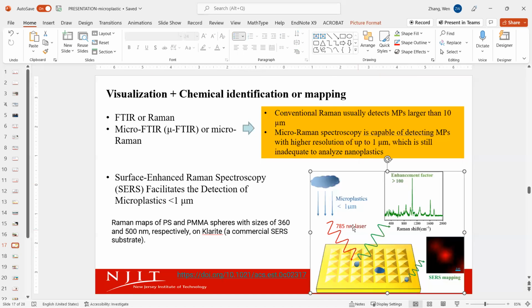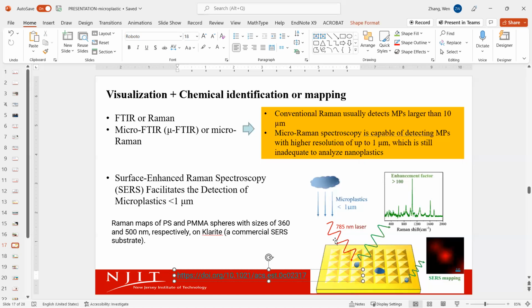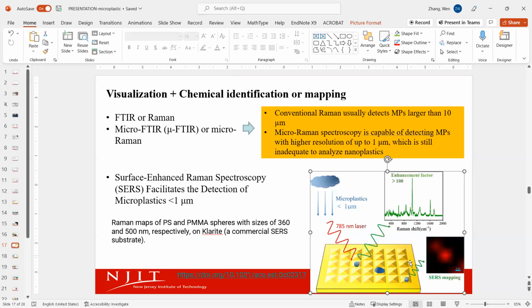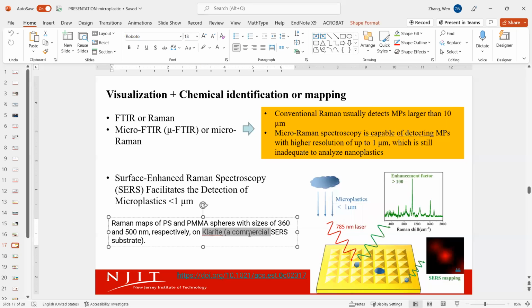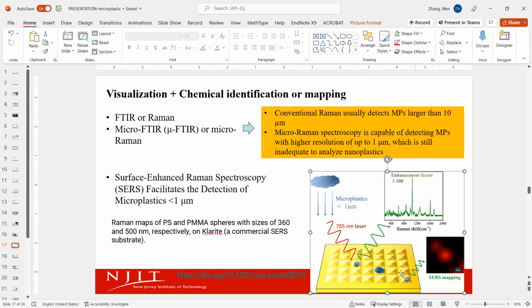For example, this is the image. This is a link to the study if you wonder about the details. What people have done here is use a commercial SERS substrate with a gold coating. On the surface of this substrate, we have PS and PMMA spheres with very small diameters, 360 nanometers and 500 nanometers. They're really small. If you use regular IR or Raman, you cannot see them. But with this design, you're able to see SERS mapping. At least you can see something with the signals.